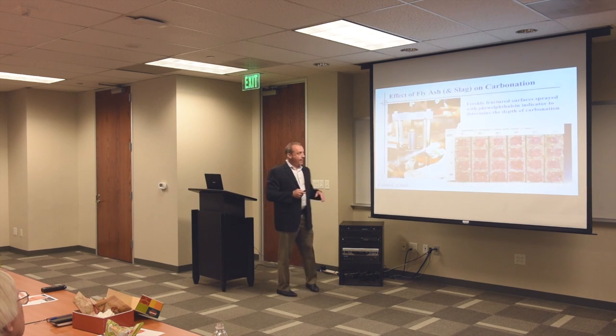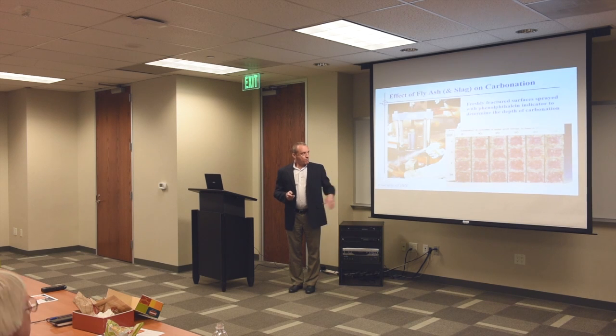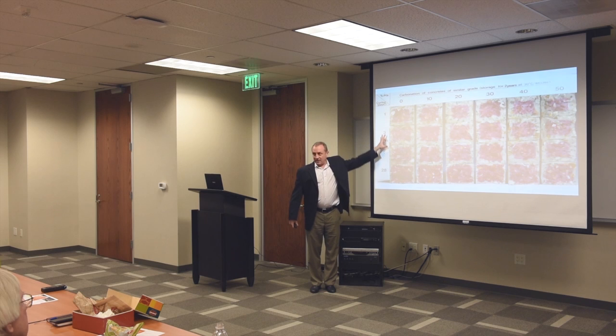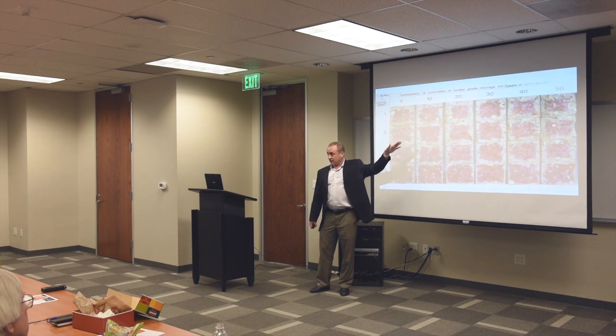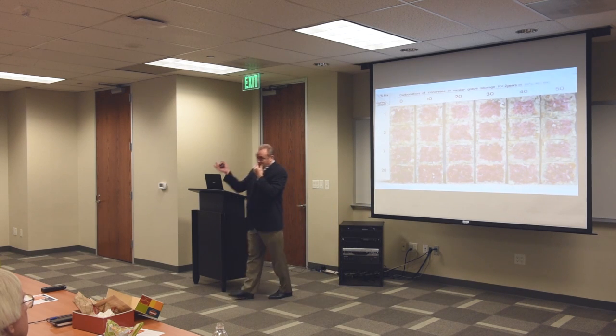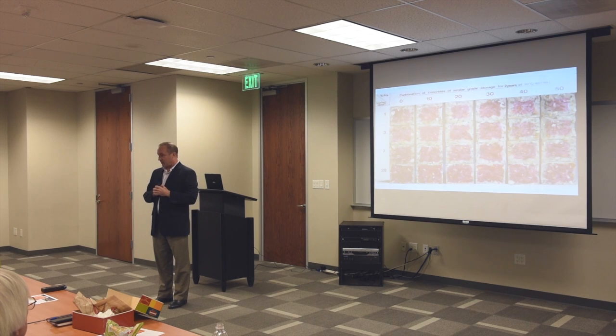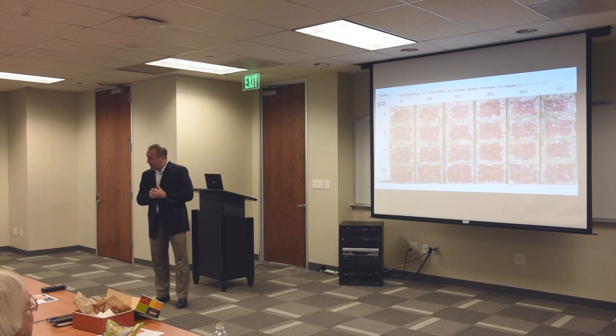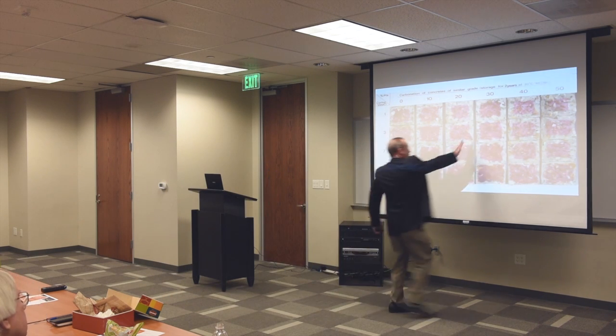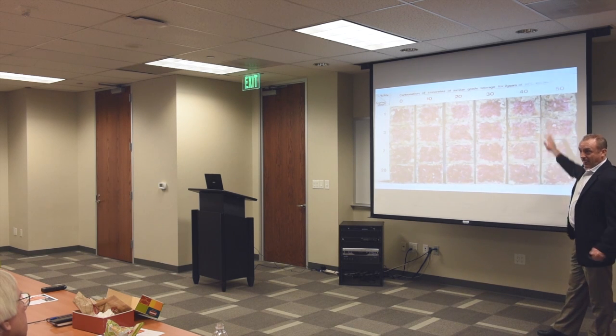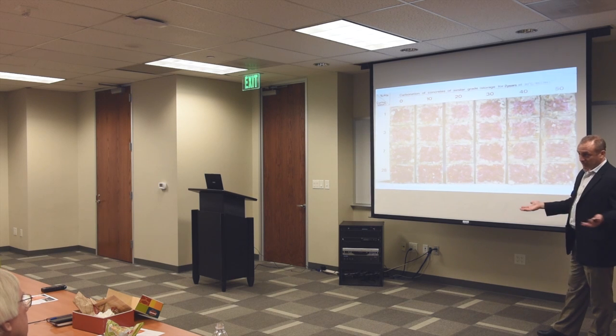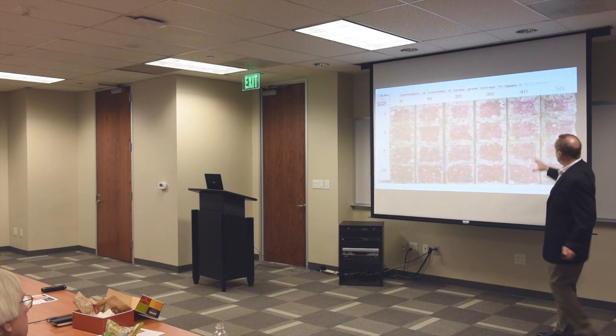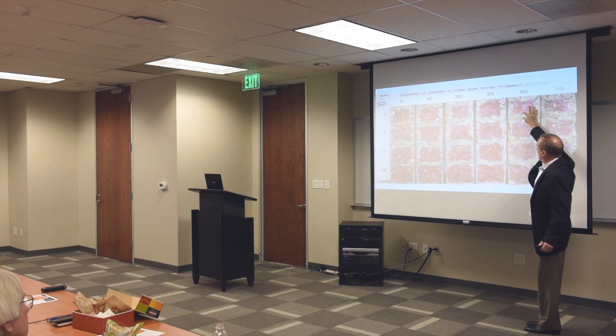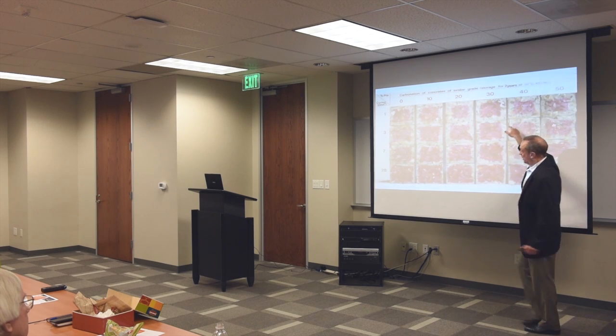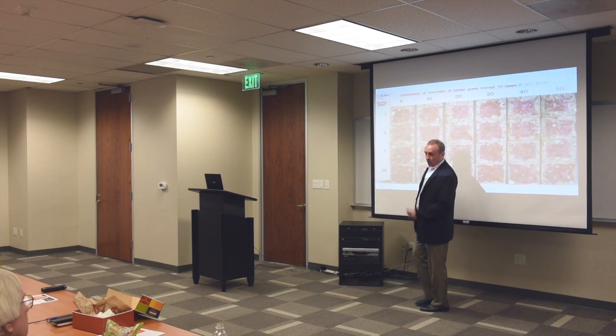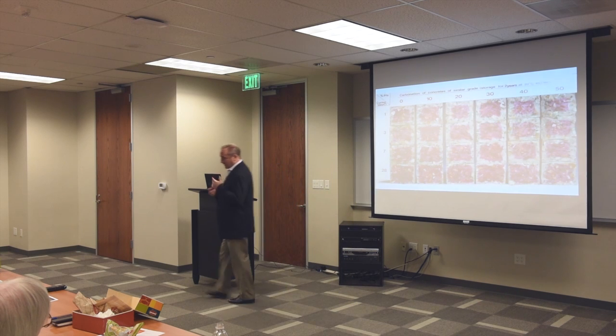To illustrate that, here's some data out of the UK. This shows curing time on the y-axis and fly ash content on the x-axis. The LEED program has really increased the amount of fly ash usage in order to reach gold or platinum status, and many of those structures will be 30% or higher in fly ash content. Typically we don't wet cure building construction hardly at all. So what you end up seeing is depths of carbonation that can be an inch or two after only a couple of years of exposure, compared to a straight cement mix that's well cured. It's one of the only cases where this high fly ash content can actually hurt you.